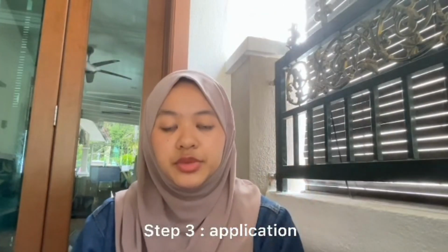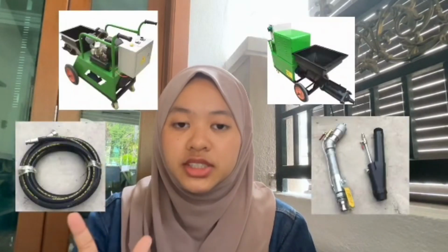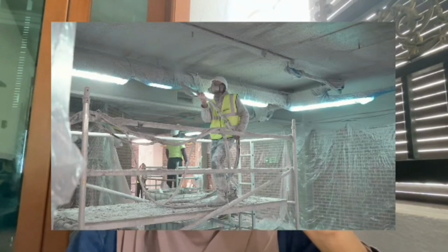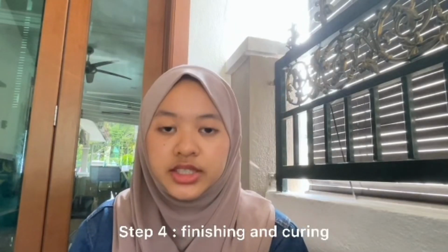The third step is application. The cementitious spray coating for steel building connection is typically applied using a hose or a pump system or a pressure spray machine, with the material wet sprayed or dry sprayed in a uniform layer. Using a steady sweeping motion, apply multiple passes as needed to build up the required thickness, which is determined by the fire rating specifications. Use a wet film gauge to regularly check the thickness of the coating and ensure it meets the project requirements. A consistent and even application of the coating is essential for achieving the desired fire resistance and preventing inconsistencies in coverage. The last step is finishing and curing.